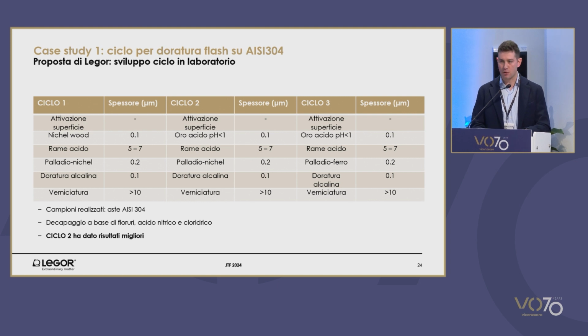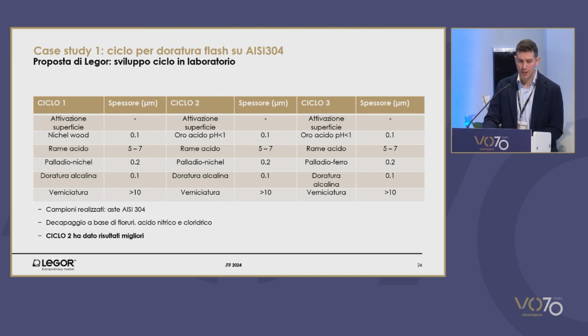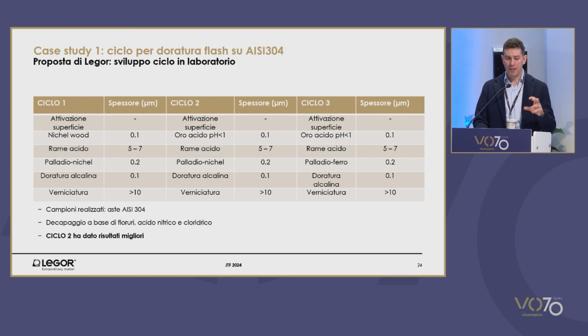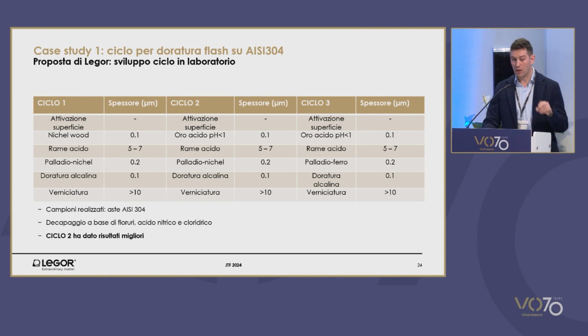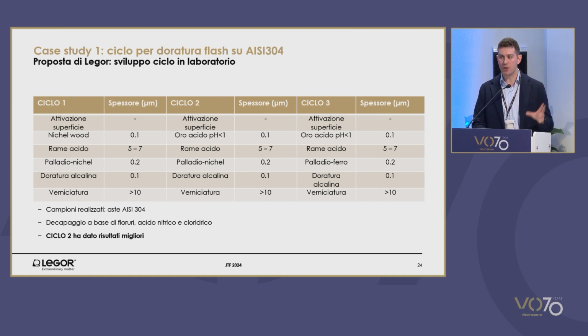At Legor, a set of studies was carried out, analyzing 3 electrodeposition cycles. The activation of the surface was a common feature, based on a treatment with chlorhydric acid. In the first cycle, nickel was still used, whereas in the other 2 cycles, gold plating with an acidic layer was resorted to.